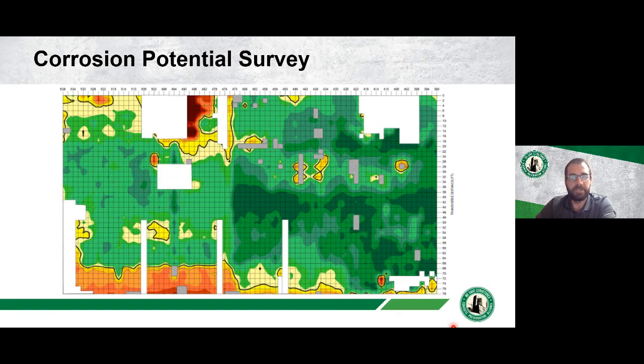So here's a corrosion potential survey of the floor in that parking garage. Here's just a small snippet. You can see a few things here. The hot colors, the warm colors, are areas where there is a high probability of corrosion activity. And the green colors are areas where the probability is low. And we see that there are also these gray hatches. Those are where the delaminations are, where delaminated concrete is. So you can see that if we just go out and repair the delaminated concrete, we're not really addressing the fundamental issues of this garage. There's a lot of active corrosion, especially here and over here, where if we don't address those areas, then corrosion is going to proceed.